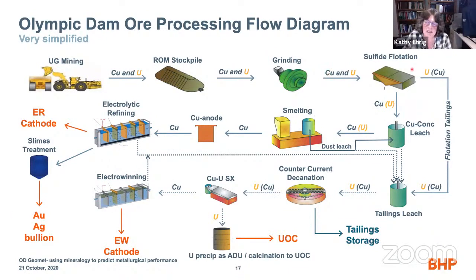Our flotation tailings, that's where the bulk of our uranium goes, about 85% of it. It goes into an acid leach circuit. We separate the uranium. Once we put the uranium in the solution, we have to separate all the uranium from the uranium-bearing solutions and a little bit of copper, from the solids. It goes into an SX circuit. The uranium goes one way. We roast it and make uranium oxide. The copper in solution, the little bit that's there, actually goes into electrowinning circuit, and we make EW cathode.